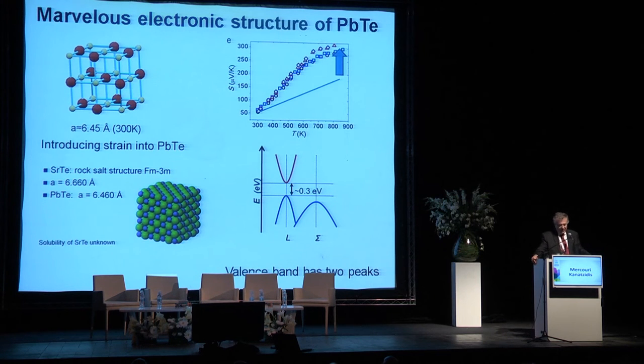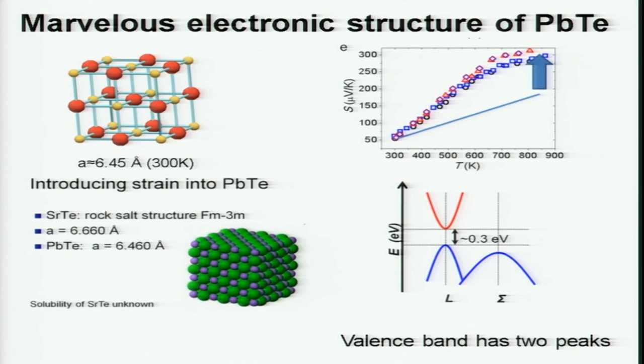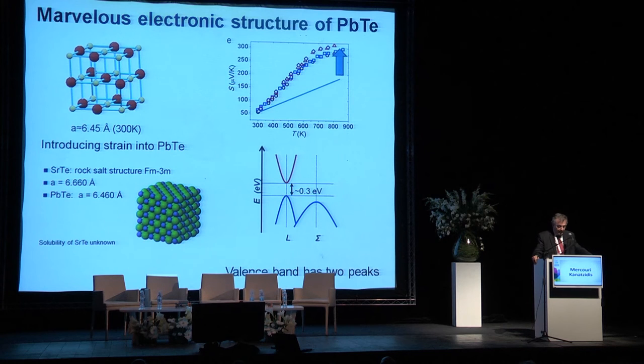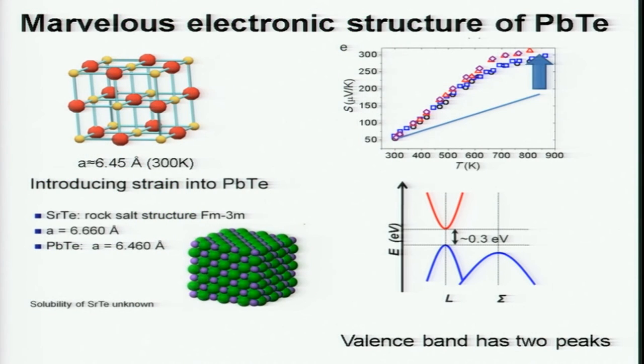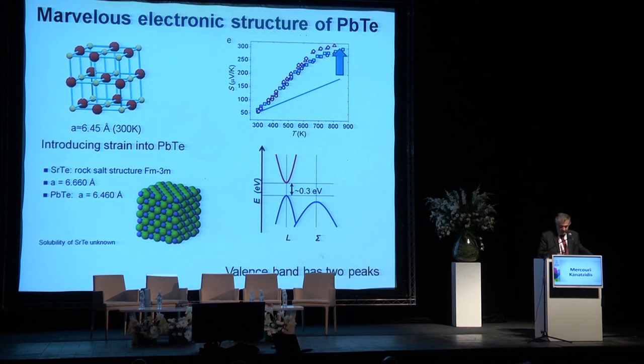So we've been working with this compound called lead telluride. It's a nice cubic rock salt structure. And in the cartoon down in the lower right, you see two blue electronic bands. And that looks a lot like the other cartoon I showed you that had the many bands. So we chose that because of these two, because we wanted to put electrons there, holes, actually, the absence of electrons. It's a different kind of carrier, to make a high thermal power system. And the upper right plot is the thermal power itself. And you see how at high temperatures, this thermal power becomes almost 300 microvolts per Kelvin, and that's a very high number. And the blue line shows you where the system would have been if it only was a single band system. Because it's a multi-band system, it has this enhancement, and you go up to 300. And so that's a great system.